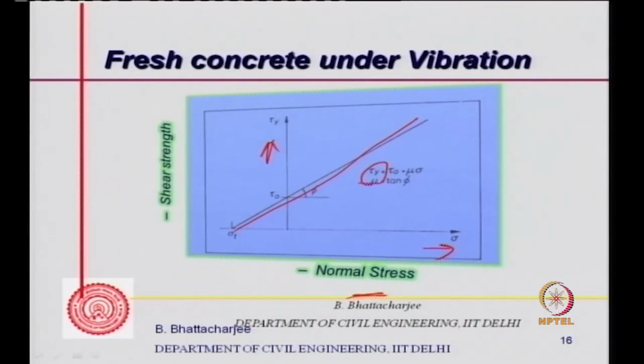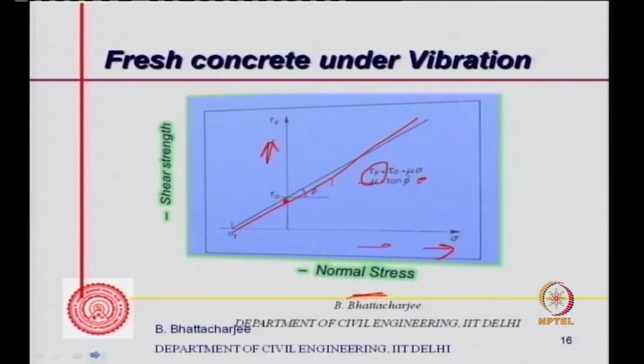So therefore, the yield shear stress tau is a function of tau 0, the intercept at this point, plus mu into sigma. So you see the yield shear stress is a function of sigma. What is yield shear stress? That was shown in the previous diagram. This is the yield shear stress. It increases with sigma. So as sigma increases, yield shear stress increases, and one can simply relate this linearly, and this is tau 0 at 0 normal stress, and of course, this is the normal tensile strength of the whole thing.